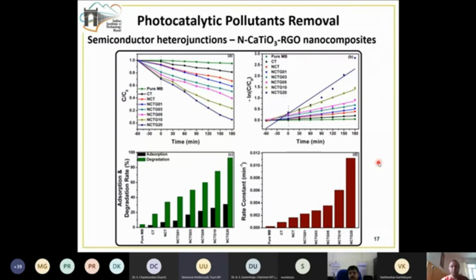And we used two pollutants. First and foremost is this MB dye, which is a model pollutant. And these are the kinetic data obtained using these samples. You can see that there is a contribution towards the adsorption, and then after adsorption, there is also a degradation. And this sample, NCTG20, gave the best result here, both in terms of the rate constant as well as in terms of the extent of degradation.